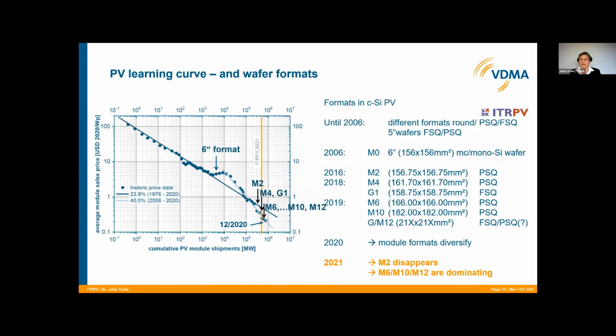Now coming to the influence of the wafer sizes, we made an insert in our learning curve for the different wafer sizes. And here you can clearly see that in the last 3 years, from 2018 to last year, we had a drastic increase in different wafer sizes, up to the G12 or M12, which we heard about just before. And we see clearly that the M2, the original long-time wafer size, is disappearing. At the moment, M6, M10 and M12 are dominating.